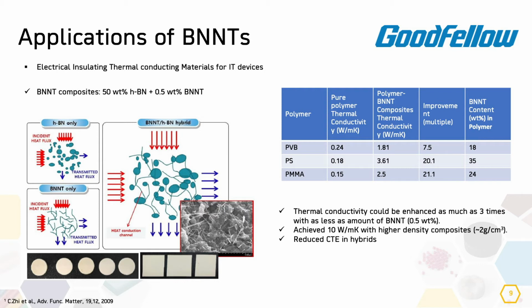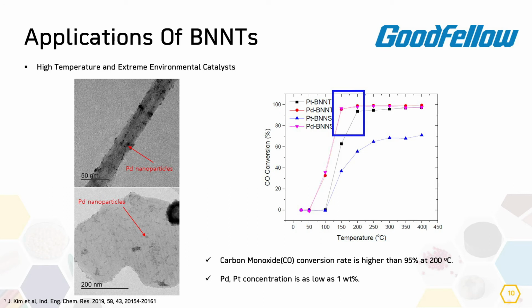Another potential application is for their catalytic effects for removal of environmentally hazardous elements, and maybe, why not, enhancing the cracking of petroleum engineering. So this material, as we can see, has converted carbon monoxide at a rate higher than 95% at 200 degrees Celsius, where carbon monoxide is usually not converted. You can also dope it with palladium nanoparticles at as low as 1 weight percentage. So in that case, the catalyst is not only palladium, and palladium is not as expensive as it would be. So I think that is a very important application as well.